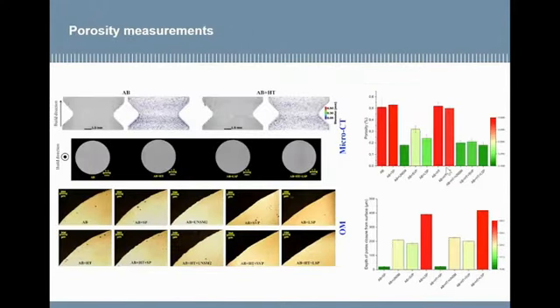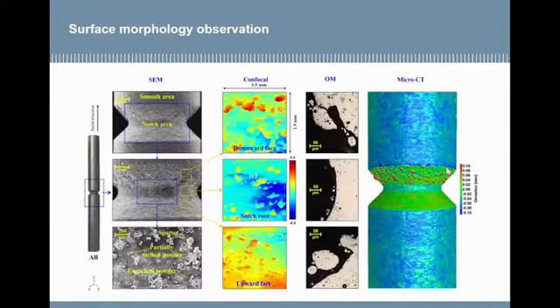In terms of porosity, again, in some cases, the treatments, especially the severe plastic deformation based ones, were able to reduce the overall porosity by closing the subsurface porosity. Especially the laser shock peening was very efficient in closing the subsurface porosity and reducing the overall porosity.